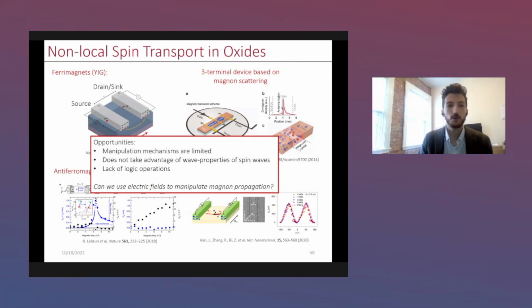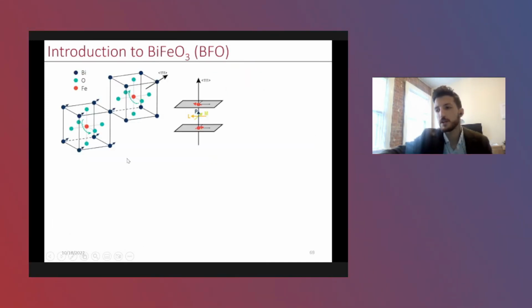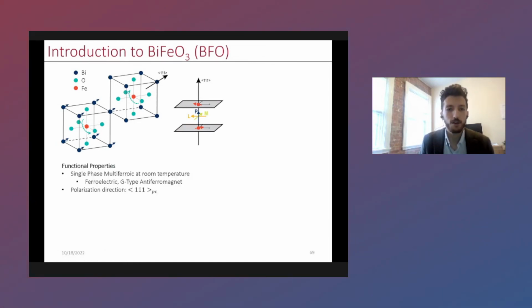So the question that we've raised is, can we use another stimulus to manipulate magnon propagation, and in particular use electric fields? And the answer is yes, and so the way we're going to do this is by using bismuth ferrite. Bismuth ferrite is a correlated perovskite oxide. It's both an antiferromagnet and a ferroelectric, where both of these order parameters are coupled. So this is the only single-phase room temperature magnetoelectric material that we know of.